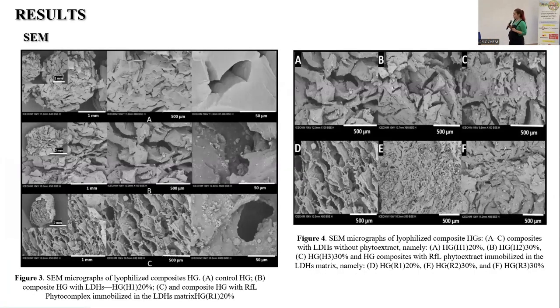The SEM results present homogeneous morphology for the obtained composite hydrogels. We can observe that the hydrogel presents a smooth and compact morphology with the LDH dispersed very well. We can also observe cracks obtained during the lyophilization process, which lead to the formation of porosity. Also, in the case of the hydrogels with LDH intercalated with phytoextract, the surface presents some elongated pores and interconnected channels.